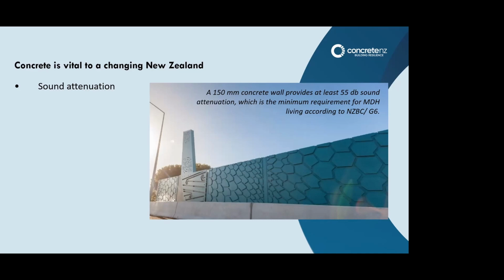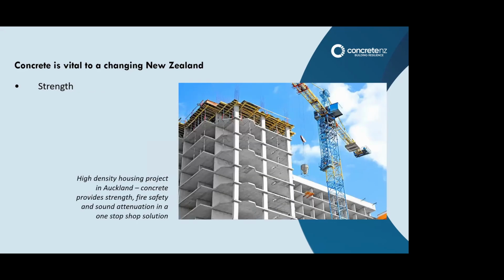55 decibel is also the minimum required for partition walls in medium density housing for compliance with our building code clause G6. Again, a 150 millimeter wall provides that, concrete, in situ or precast, or a 200 millimeter or 190 millimeter fully filled concrete masonry wall. So the sound attenuation, that's a big feature of concrete structures.